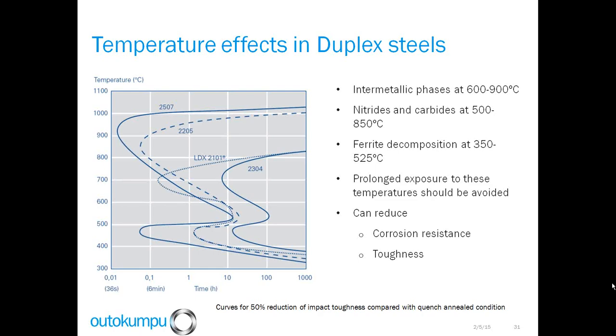Temperature effects, I mentioned this earlier, is why we want to make sure that when we get below 900 degrees C the material is quenched. Between 600 and 900 degrees C we have the potential for intermetallic phases. In the 500 to 850 degrees C range, we have nitrides and carbides that can precipitate. And then from 350 to 525 we worry about ferrite decomposition into alpha prime. So again, you want to reduce the time at temperatures in these ranges. The reason is we want to keep the good corrosion resistance and toughness of the weld, the heat affected zone and the material by rapidly cooling.